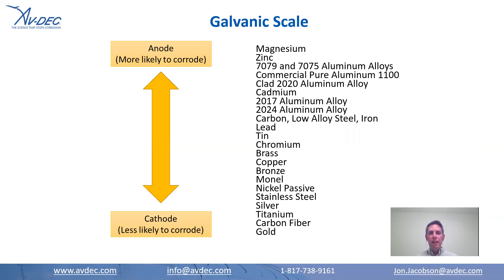Here we have the galvanic scale. At the top of the galvanic scale, we have our anode materials — those are more likely to corrode. At the bottom, you have your cathode materials — those are less likely to corrode. When you have two materials next to each other, if they're farther apart on the galvanic scale, you have a higher likelihood of corrosion on that anode material. At the top we have magnesium, some different aluminum alloys like your 7075s and 2024s. At the bottom we have titaniums, carbon fiber, and stainless steel. If you have carbon fiber next to an unprotected aluminum alloy in the presence of an electrolyte, you have all the necessary conditions to start galvanic corrosion.